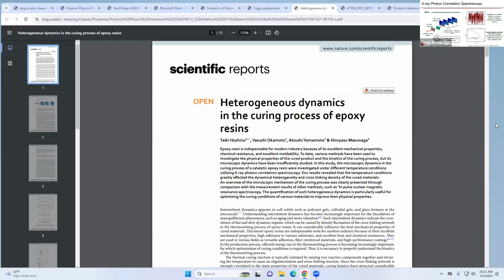We're at short time scales, so frames that are all right next to themselves. If things aren't changing very much, they're going to be highly correlated, right? So that means our function is going to have a big value. So up here, it means that from frame to frame, things haven't changed that much. And if I think about that on the nanoscale, that means that those things aren't really moving, right? But as I go longer and longer in time, because things are moving around, those frames start to look a lot more different. And that function starts to decorrelate or decay over time. Where at long time, my image from the beginning and my image at the end don't look alike at all. They're completely different, which means that my arrangement has fully reorganized itself at that nanoscale, right?